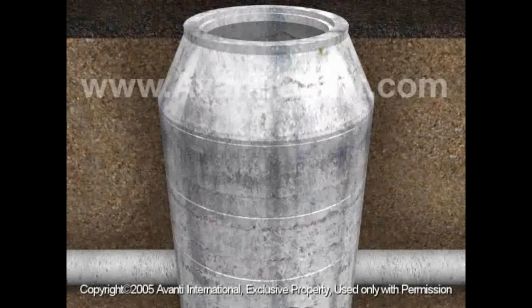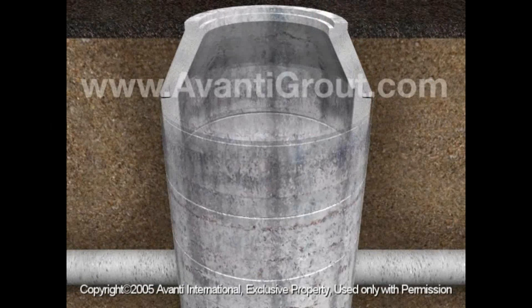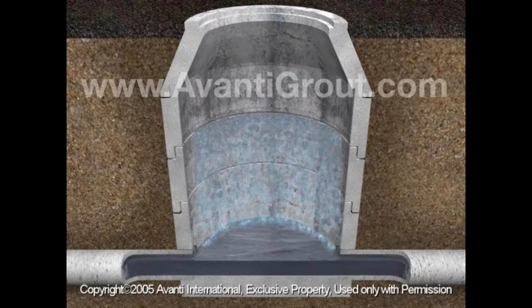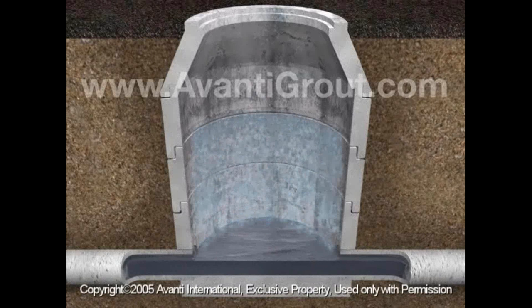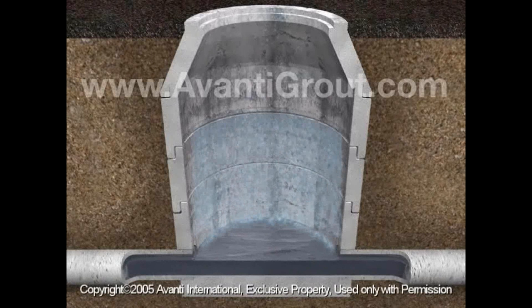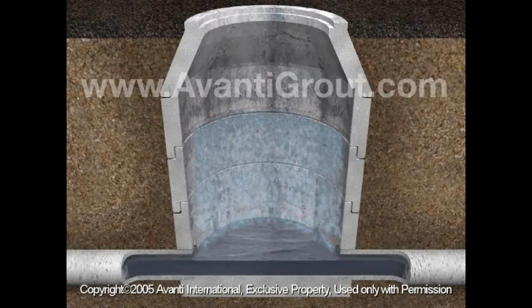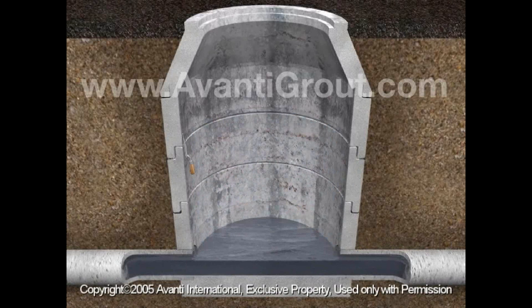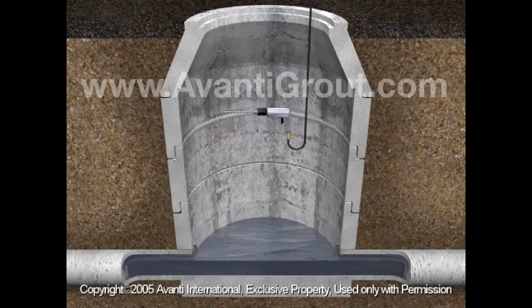In the horizontal crack injection animation, you see the leaking manhole. Injection holes are drilled in a horizontal pattern. You would then again flush the cracks with water to remove any debris and then install the injector. You're not trying to drill all the way through the structure wall, so again, keeping in mind the thickness of the wall is important.